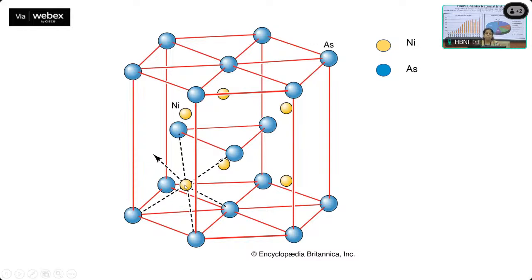If you remember, or if you can see it here, the octahedral holes lie exactly above one another. Only their Z coordinates were different. It was 2/3, 1/3, 1/4, and 2/3, 1/3, 3/4. That means each arsenic is surrounded by 6 such nickels. That means the coordination number of arsenic is 6, similar to what nickel had.